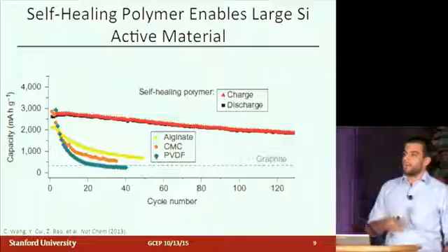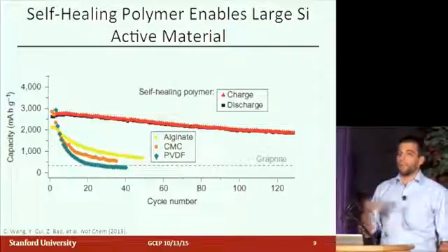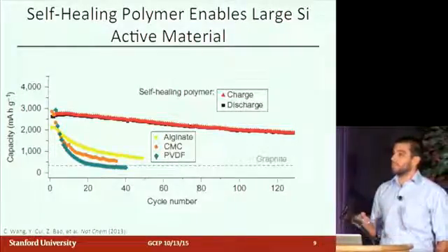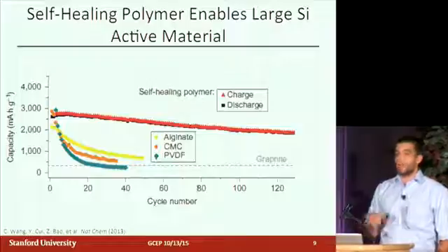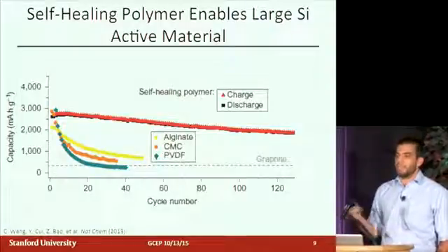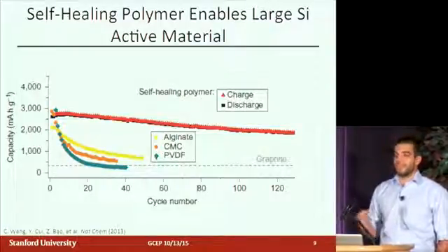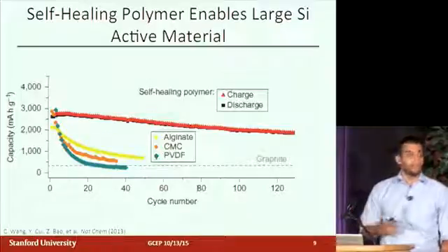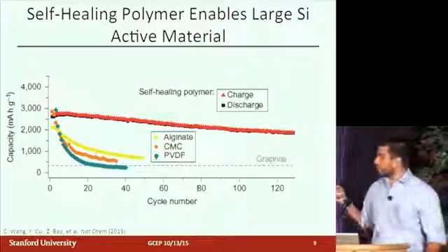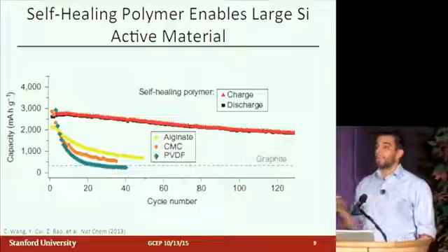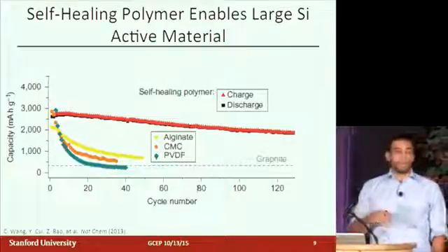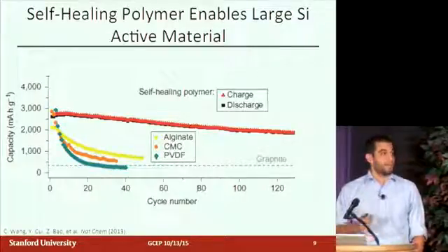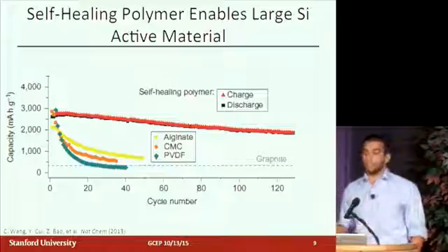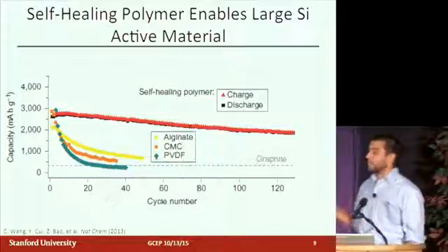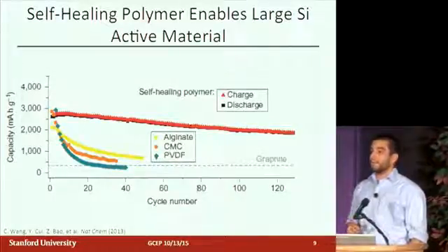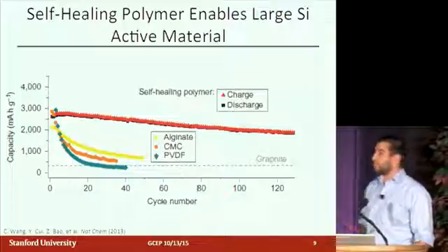And all of those studies I talked about before, the polymer binder studies, they all use small nano-sized silicon particles as well. Not nanostructured particles, but still small particles that don't fracture because they're below that 150 nanometer critical dimension. And so what we're doing here instead is using about micron-sized particles. And these are about an order of magnitude or 2 cheaper than the nano-sized particles, which is why we're excited about them, and that we can get cycling stability that's comparable to the nano-sized particles, but with a much cheaper material.